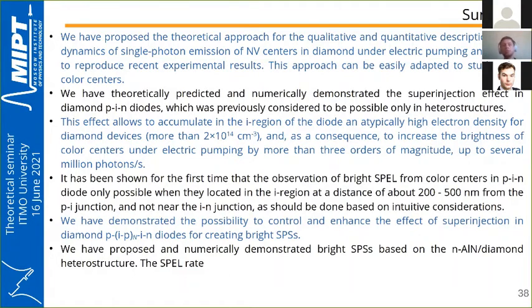It has been shown for the first time that observation of bright single-photon electroluminescence from color centers in p-i-n diodes is only possible when they are located in the I region at a distance of about 200-500 nanometers from the p-I junction, and not near the I-N junction, as should be done based on intuitive considerations.